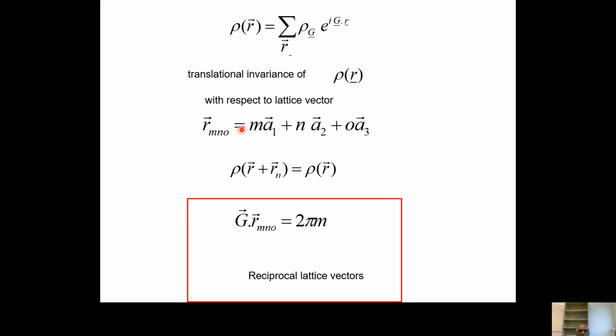Okay, now another important thing is this rho(r), the charge density, right? Of the many properties in a crystal, that's a very important thing. In crystals, we have spatial or translational symmetry, even for the electron density. So that means I should be able to write rho(r) as a sum of terms, where G is the reciprocal lattice translational vector.